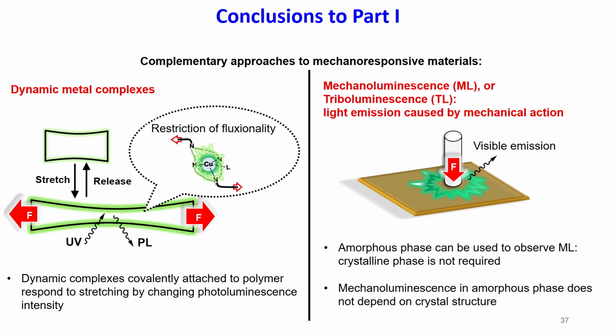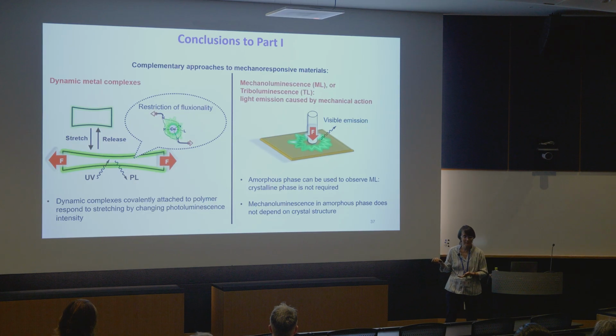So with this, let me summarize the first part of my talk on making mechanoresponsive material. In our group, over these past several years, we've developed two approaches to make mechanoresponsive materials, and they complement each other. So one is based on the dynamic behavior of the photoluminescent metal complexes that we incorporate into the polymer. That allows us to very quickly see very fine changes in the photoluminescence intensity in response to stretching on a millisecond timescale.